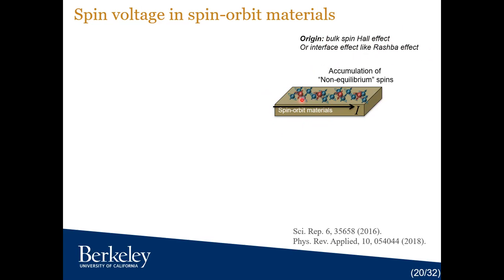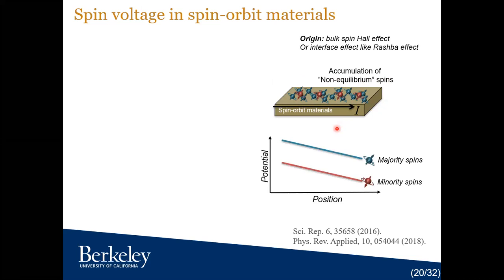If you run a current, you create a spin accumulation of non-equilibrium spins. And by non-equilibrium, I mean if you turn off your voltage or current, these spins will go away. And in spin accumulation, the majority spins are, let's say, up, and minority spins are down. When you have a collection of electrons, you have a potential, and now you have spin polarized electrons, so you have spin potential. Since majority spins are high in number, the majority spin potential will be higher and minority spin potential will be lower. And this gap, the difference, is called the spin voltage, and that's constant along your channel,